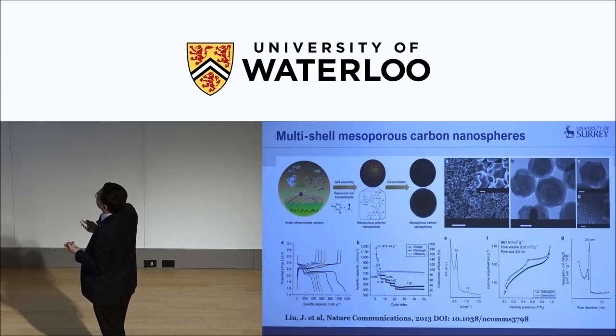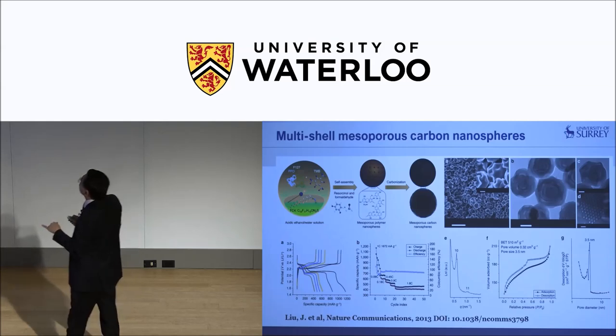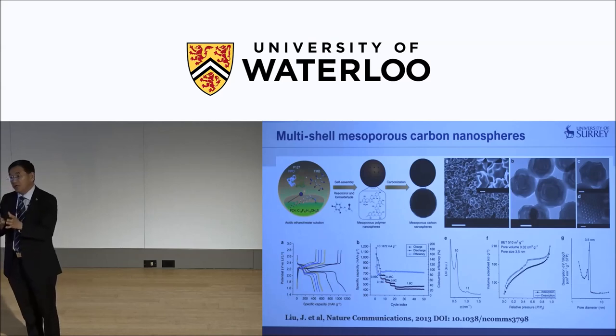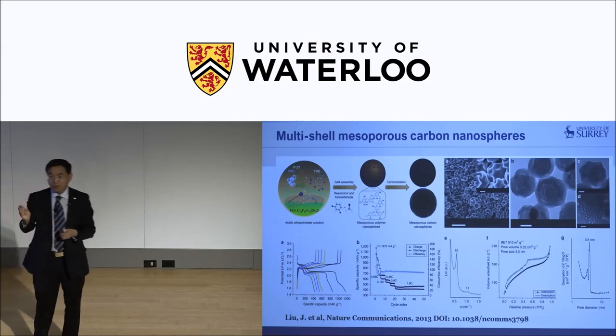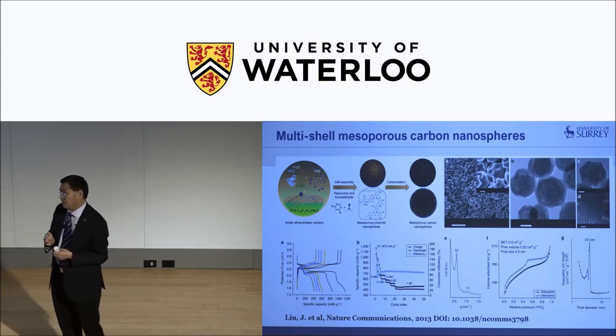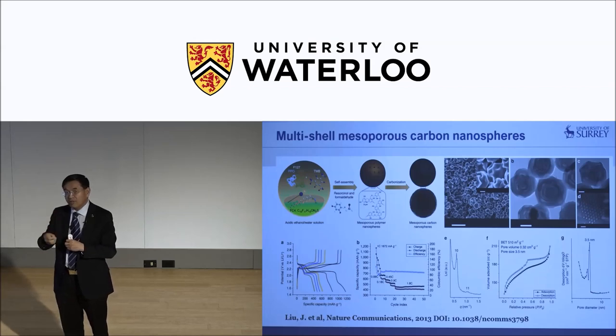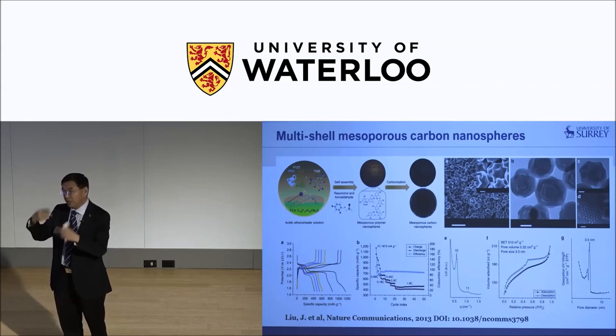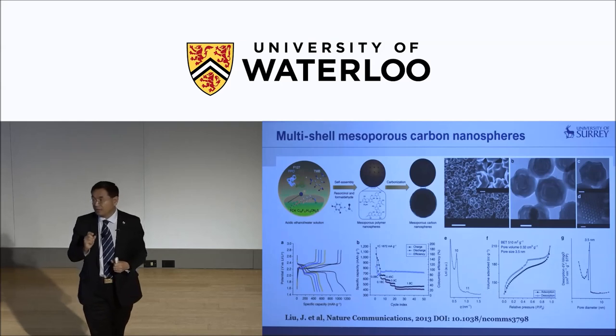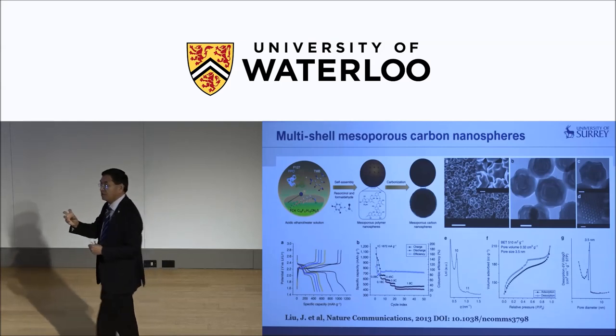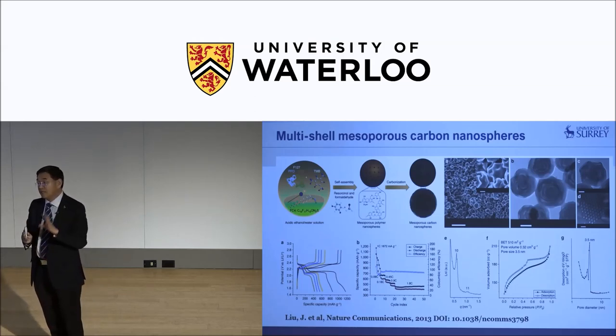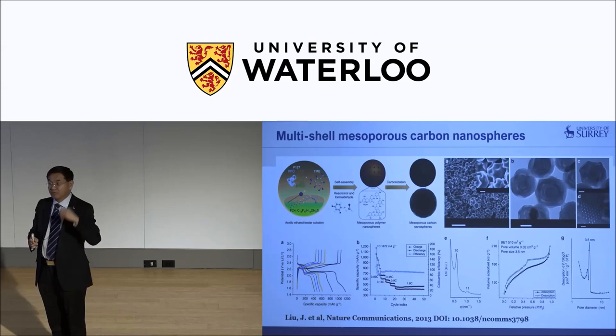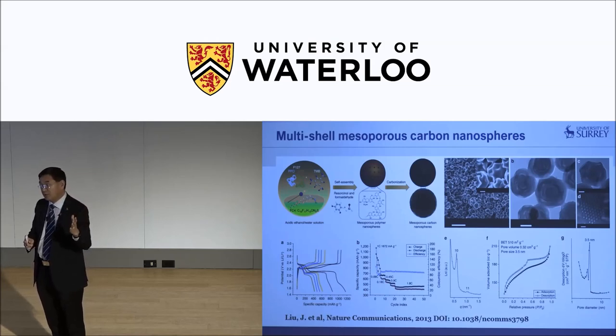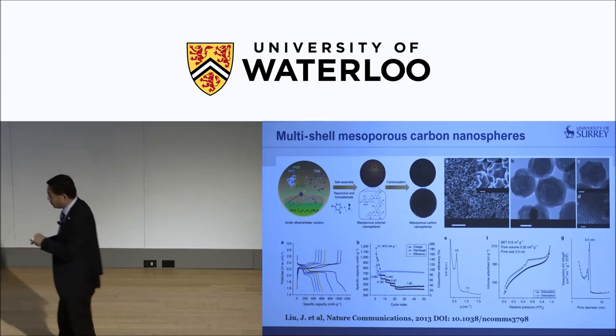And you can see the characterization. So he did control the pore size to be around 3.5 nanometers. In fact, in earlier work in lithium sulfur, we found that any pores that are larger than 6 nanometers are not effective because the lithium polysulfide dissolves in the electrolyte and gets lost when the pore is too big. And predominantly between 1 and 6, you have this confinement effect of the sulfur and therefore maintain the stability. And we all know lithium sulfur battery gives extraordinarily high capacity, and this recyclability is enhanced by the stability. So this work demonstrates that.